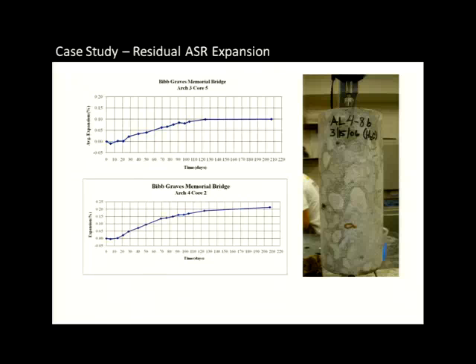And what we could see from a core from Arch 3 was a fairly moderate level of expansion up to about 0.1%. And then in Arch 4, we see a continued level of expansion all the way out to about 130 days, up to about 0.2% expansion. So what it's telling us is that the concrete in Arch 4 still has the propensity to expand, and we need to try and do something about it. And there is the potential for expansion in Arch 3 also. So we have monitoring set up so that we can see if that arch is going to start to expand on us as well.